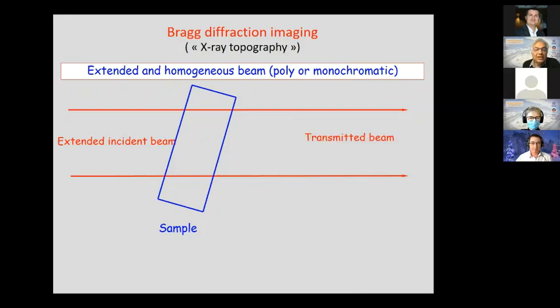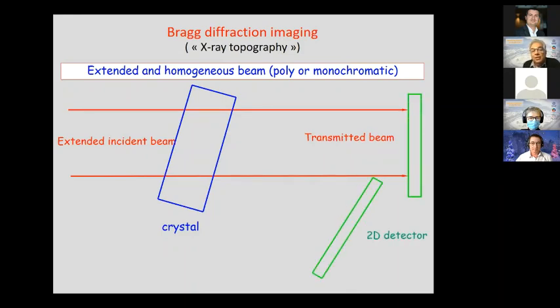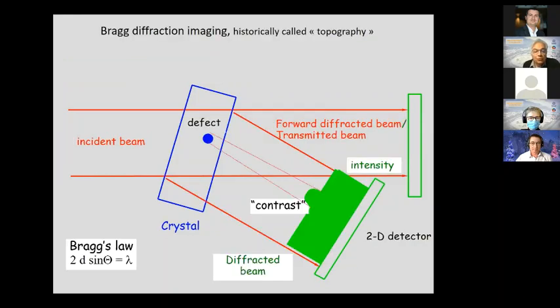Of course, you have a transmitted beam, which can give you a radiograph. But if your sample is a crystal and you turn your crystal to be in Bragg position, that is, fulfilling Bragg's law, well, you have a diffracted beam you can record into a detector, and the intensity recorded in that detector is more or less uniform if your sample is homogeneous. But if your sample has a defect, you have contrast in your recorded image, and from this contrast, you can go back to the defect you have in your crystal.